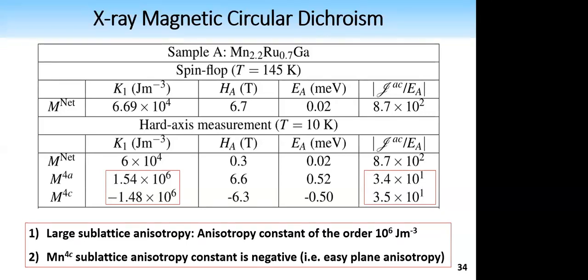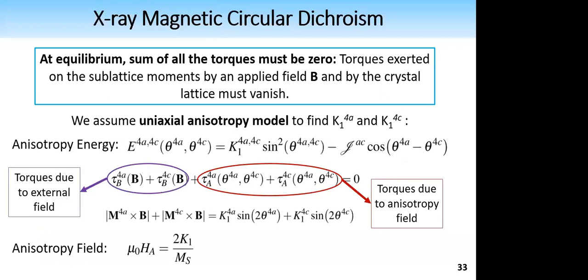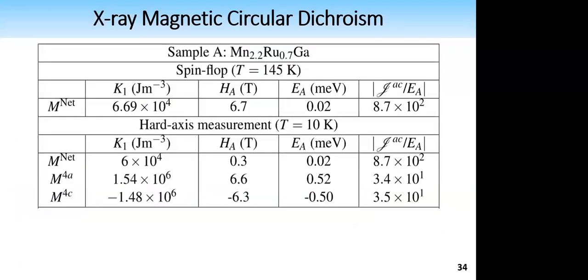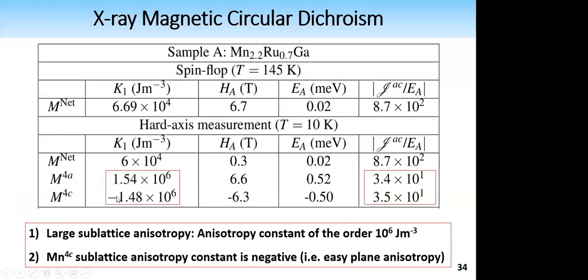So what could this possibly mean? I believe there are 2 possible contributions here. The first one is that because of the simple uniaxial anisotropy model, we've assumed in this energy equation that the JAA and JCC intersublattice couplings are infinite, which is not the case. Also, this uniaxial anisotropy model does not take into account non-collinearity. So perhaps one explanation for these results would be that this is a manifestation of the non-collinearity, which is not quite captured by our model.